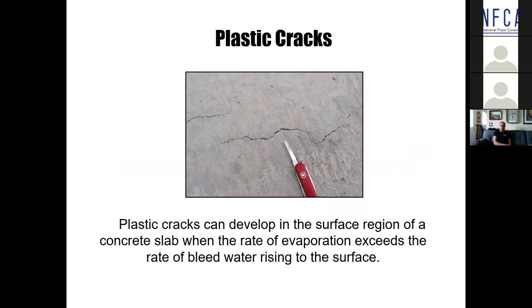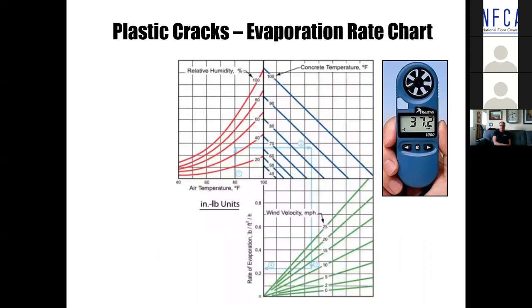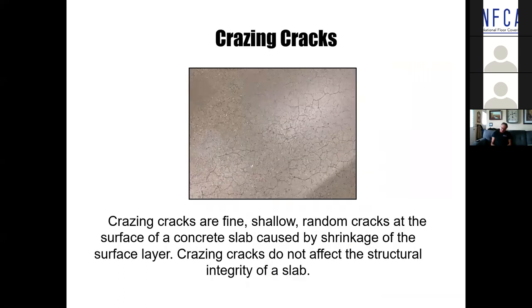You get a hot, dry climate with wind. The moisture that's evaporating from the surface is not being replenished by the bleed water, which can lead to superficial plastic cracks. There are ways today, very easily, for a finisher or a GC or a project manager to know whether they're at risk. You take the air temperature, you come across to what the concrete temperature is, come down to measure your wind with this little handheld unit, come across, and you can tell whether you're at risk. And there are things you can do. There are monomolecular films that you can spray on the surface, not curing compounds, that minimize the potential for plastic cracks to develop.